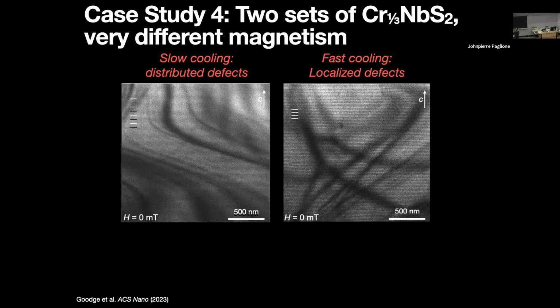But yes, that is precisely, I think, what one would need to do: try to understand how to use that sort of post-synthetic thermal treatment to really obtain a long-range 2x2. I think of it almost as a crystallization problem, but now the crystallization is of the intercalants in the interlayer. Normally when you're cooling down from high temperature, by the time it becomes energetically favorable to form the 2x2, because the enthalpy crosses over the entropic, you're at a high temperature, and so you nucleate the 2x2 domains really fast.